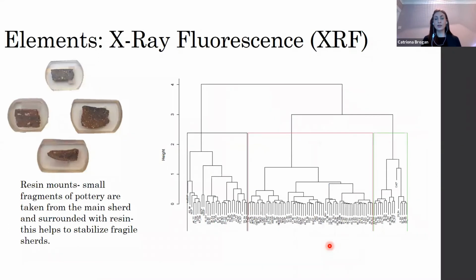Then we also use X-ray fluorescence, and basically this gives us the elemental oxides present within each pottery or clay sample. And once again, you can use a resin mount, in which you have a small piece of pottery mounted within a resin platform, and the resin mounts are quite good for very friable pottery like the prehistoric stuff because it helps to stabilize them. But the X-ray fluorescence then identifies the different oxides that are present within the sample, and also their relative percent as well.